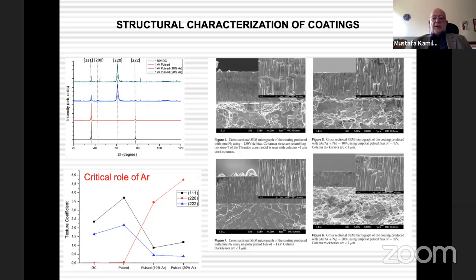So what we did, in this case, was compare the coatings that have been produced by DC bias, this is the DC bias, and then 1 kilovolt, that means a 1000 volt pulse bias. And then we also introduced argon into the structure. What we saw is that when we have argon in the structure and also apply pulse bias, we end up changing the orientation of the titanium nitride films that grow into the 2-2-0 direction. So these films are normally 1-1-1 oriented, but when we apply a high voltage pulse bias, we start to grow films in 2-2-0 orientation, and additionally, we also got a finer columnar structure.